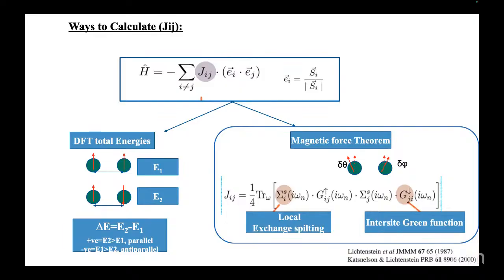So one needs to calculate the Jij interactions, and further, if we want to be more precise in knowing whether it is collinear or non-collinear, one has to go beyond this approximation into atomistic spin dynamics to completely say whether there is non-collinearity or collinearity. So basically, in the whole of your calculation, the effect of tin is just to determine the dimensionality of the system? Tin is a heavy metal, so when we include spin orbit coupling, it might affect the anisotropic part of the exchange interactions. So we expect some kind of effect coming from the tin. In later slides, I will discuss that.